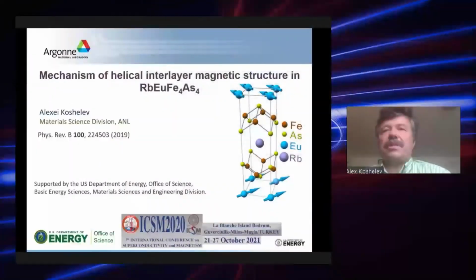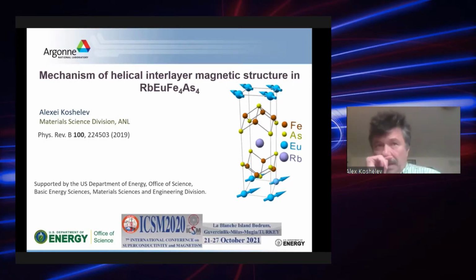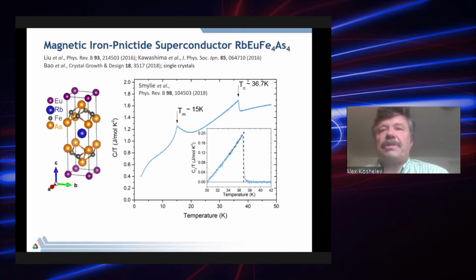Interlayer magnetic structure in rubidium europium iron 4 arsenic 4, and this is quite a peculiar material which has a superconducting transition at a temperature of 36.7 Kelvin, followed by a magnetic transition deep inside the superconducting state related to ordering of the europium sublattice.